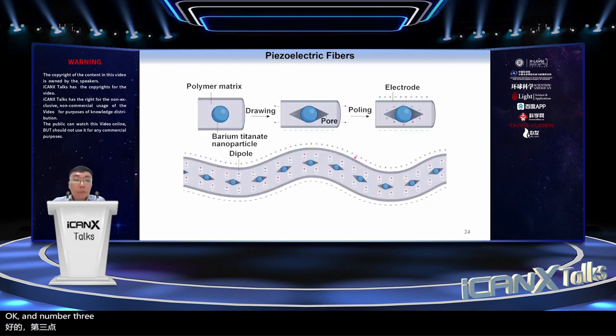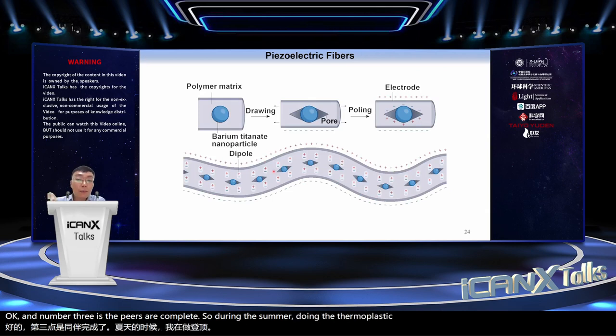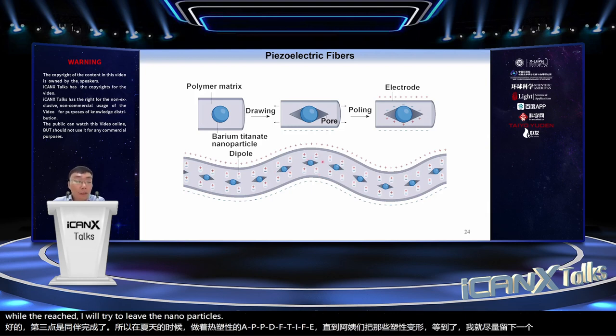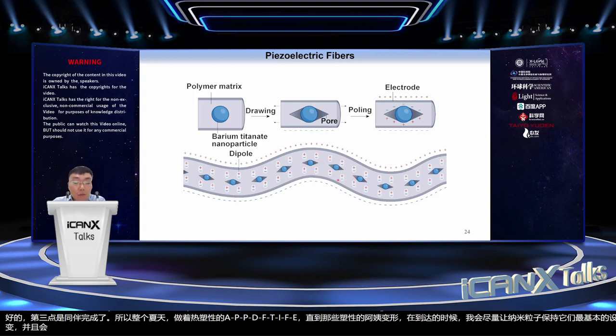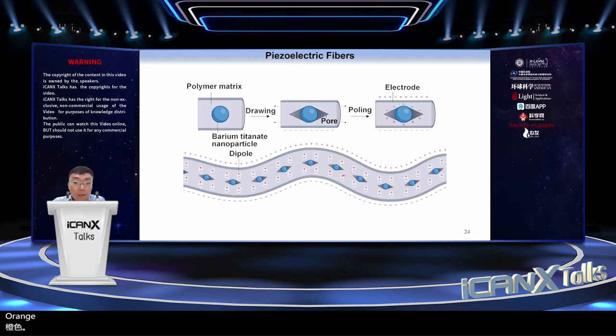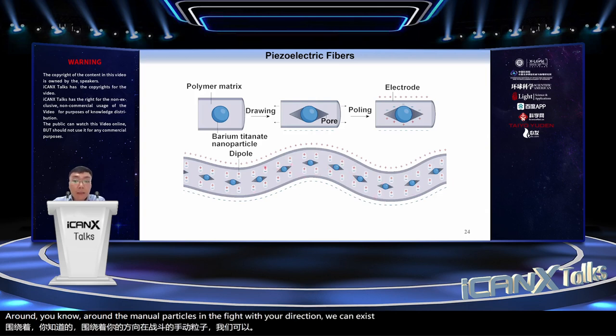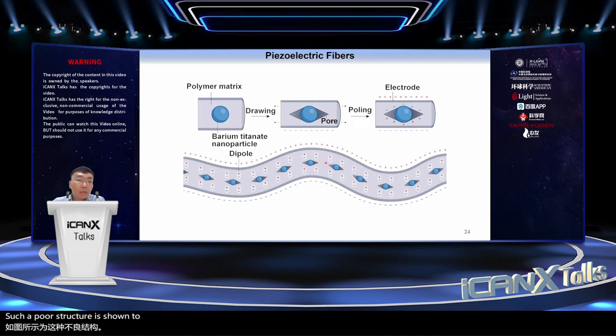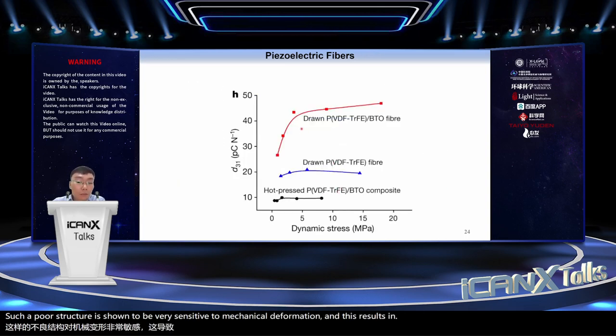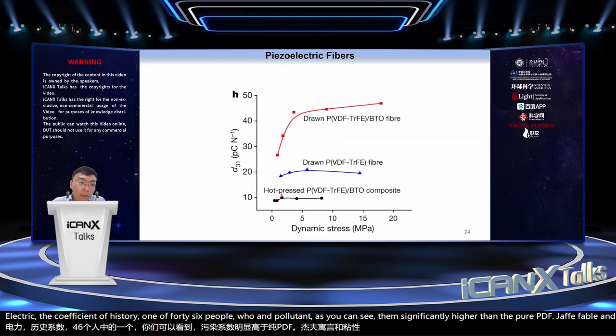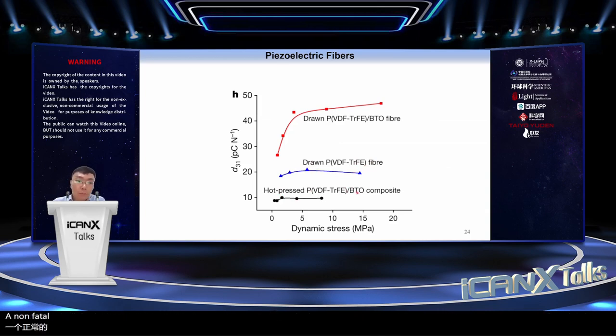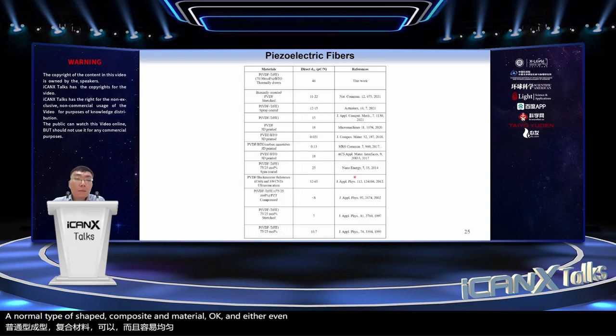And number three is the piezo composite. During the thermal joining, the thermoplastic PVDF-TrFE undergoes plastic deformation, while the rigid titanate nanoparticles maintain their morphologies unchanged. This induces the formation of pores around the nanoparticles in the fiber axis direction. Such a pore structure is very sensitive to mechanical deformation, and this results in a piezoelectric coefficient d31 of 46 picocoulomb per Newton, which is significantly higher than the pure PVDF-TrFE fiber, significantly higher than the hot-pressed, non-fiber-shaped composite material, and even higher than many PVDF based materials and devices.